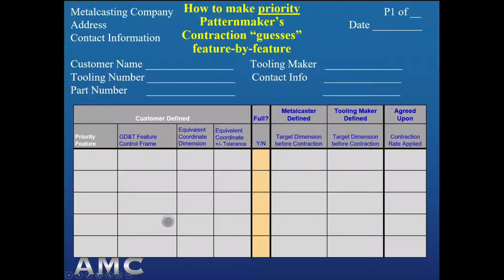Now, look at this center column labeled full, marked in light orange. Full means that after we chose the contraction rate, we built the tooling on the large side of the dimensional range. For risky dimensions, that meant that when we missed the contraction rate, which we sometimes would, all we had to do was remove some tooling material to fix it. With metal tooling especially, having to add small amounts of material to the tool is a disaster for tool life.